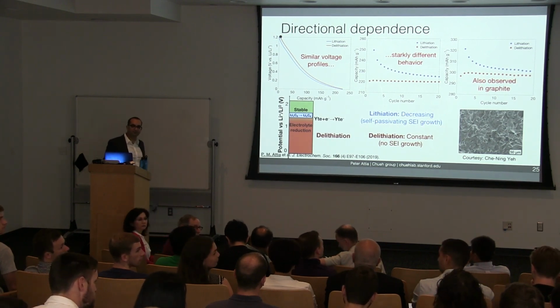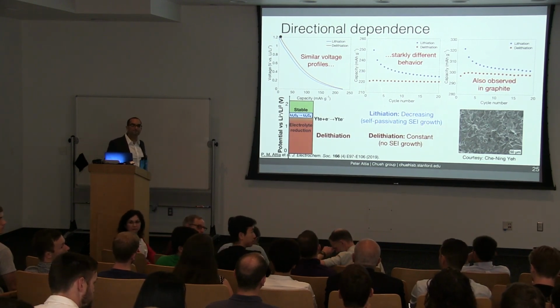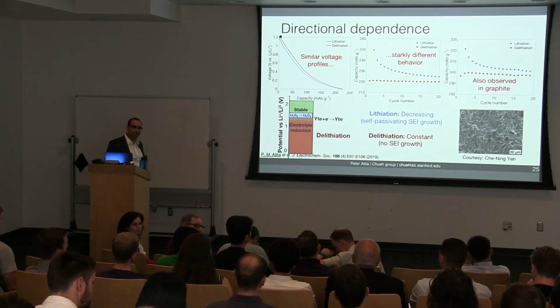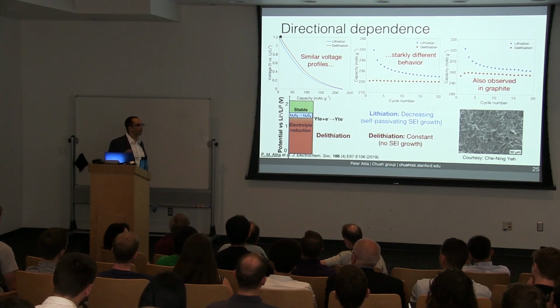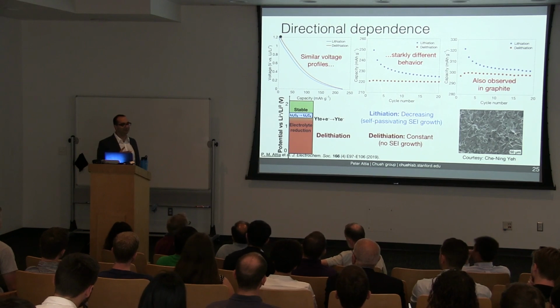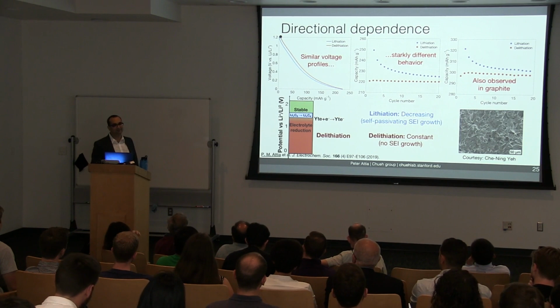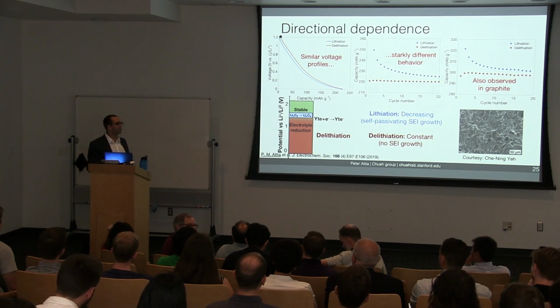Those lines you mentioned, the dynamic nature of the kinetics you're seeing for SEI growth, will that be similar for silicon, lithium, etc.? Why do you think that? I don't necessarily know if they translate directly from this. I think that the dynamic nature of the kinetics should be modeled in all of the systems. Fundamentally, if we model them statically, we're missing key effects like this direction dependence.